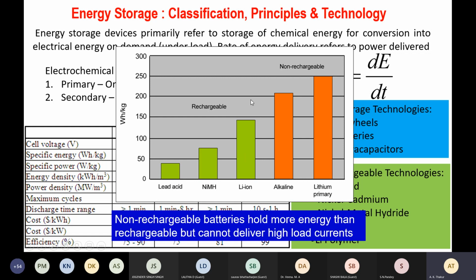Whereas a lithium ion battery has a discharge rate of around 1% per month, lead acid cells have a discharge rate of around 8 to 9% per month. And this is why, when we don't use our vehicles that use lead acid for starting ignition, after 2-3 months its energy goes down and ignition creates a problem. It creates another problem in the winter when there is chilly weather, at that time also it creates problems in ignition.